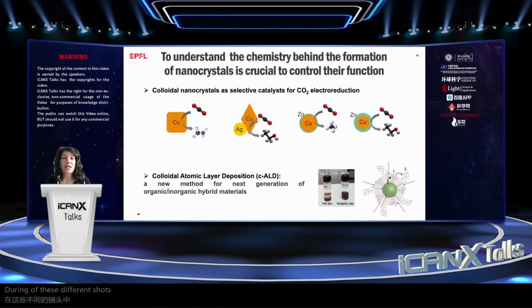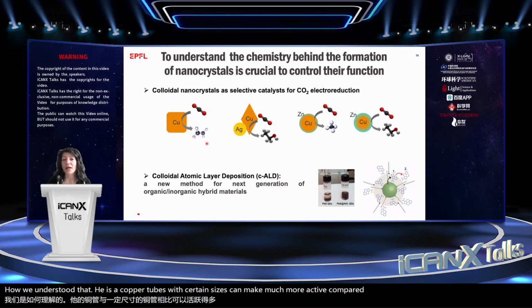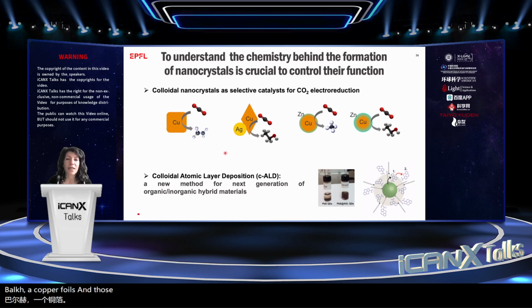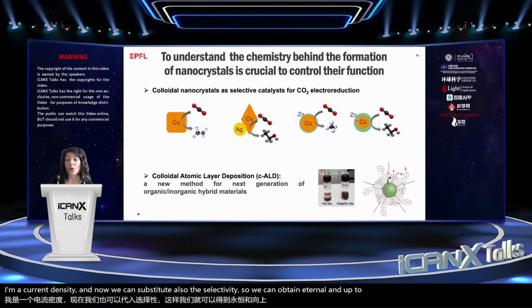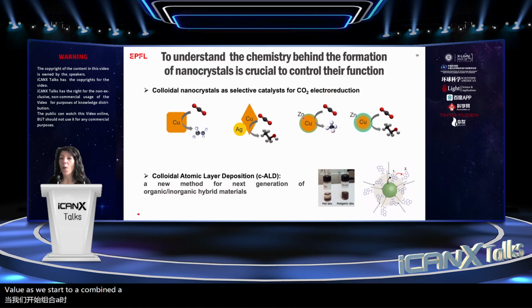And with this, I'd like to wrap up the talk by highlighting again that understanding the chemistry behind the formation of nanocrystals is crucial to control their function. And so this well-defined catalyst I showed you in the first part of my talk, how we understood that these copper cubes with certain sizes can make much more ethylene compared to bulk copper foils, and also compared to single crystals, especially when we are interested in commercially relevant current density, and how we can start tuning also the selectivity, so we can obtain ethanol, up to 40% of ethanol, which is a state-of-the-art value, as we start to combine copper with different elements.